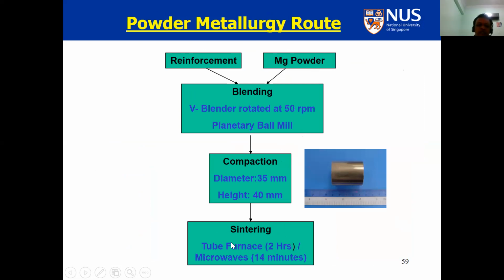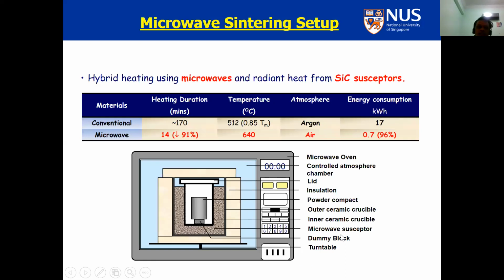For sintering, people use tube furnaces. It takes about 2 hours for a 1.5 inch thick sample, but we try to move on to the microwave because it's an energy saver. So what we did was use a microwave exactly the same as what you use in your household. We created a setup for the insulation here. Here's an inside crucible. Here's an outside crucible. Between that, we put the silicon carbide particles. We put the billet in here that needs to be sintered.